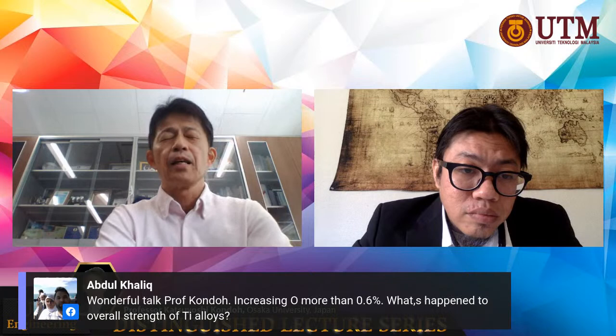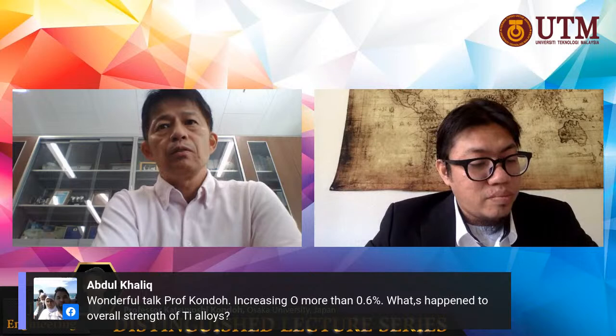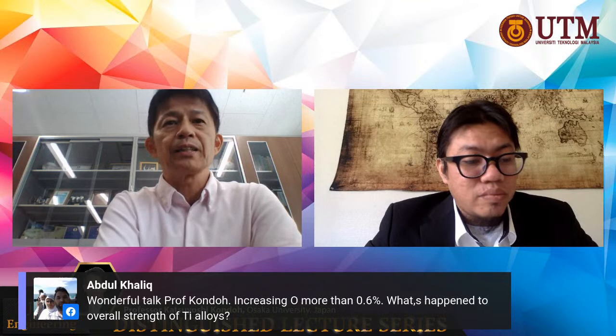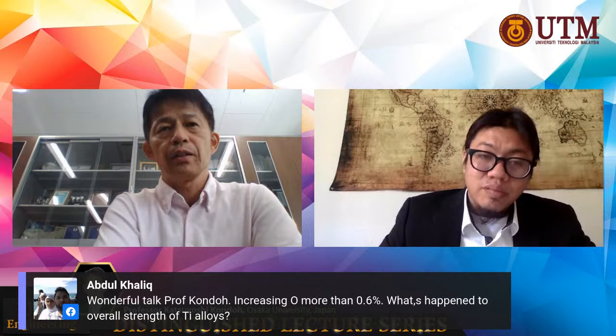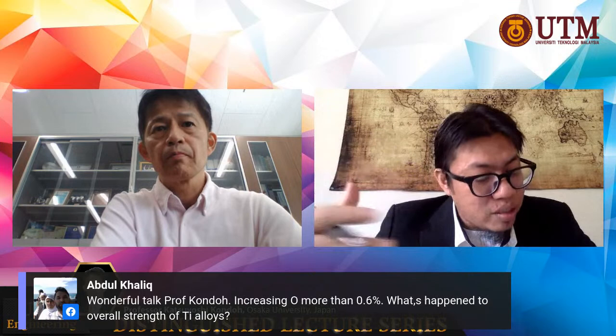Okay. We have our data until about 0.9 percent. Over 0.9 or 1% oxygen content, ductility decreases. Ductility decreases because of the slip system change of alpha titanium. As a result, unfortunately, the elongation suddenly decreases. I see, so it is a trade off: the slip system changes and ductility drops off if we further increase the oxygen.